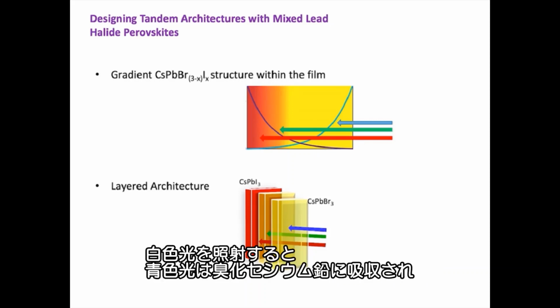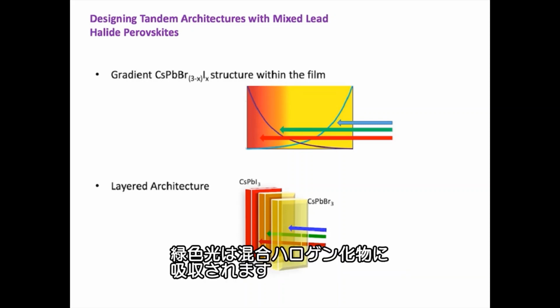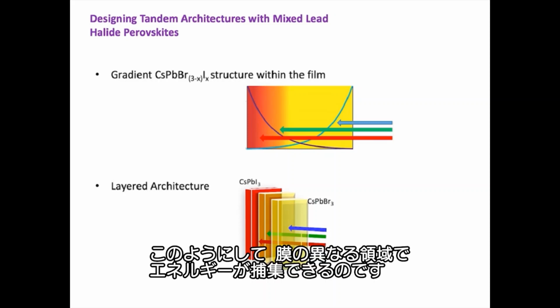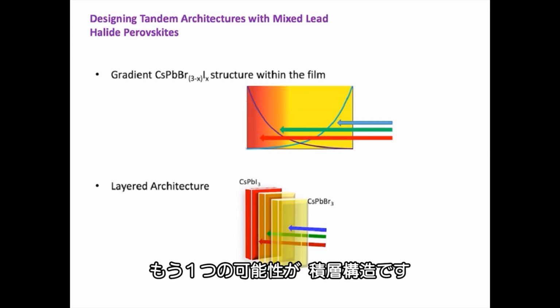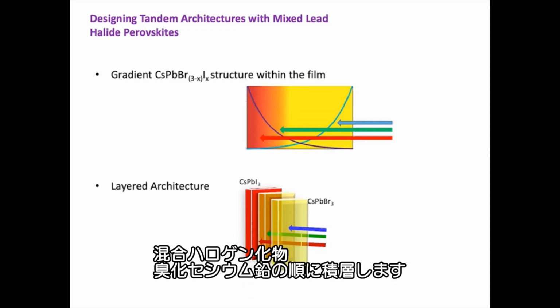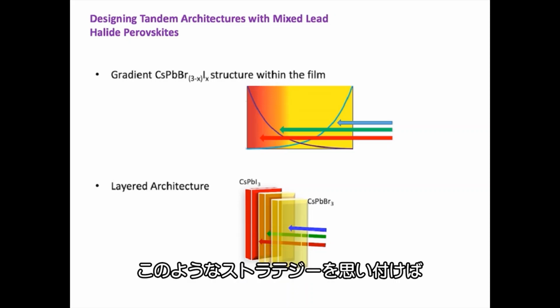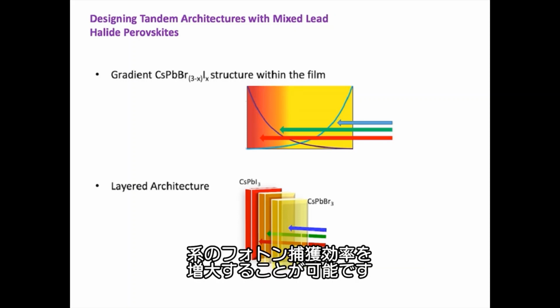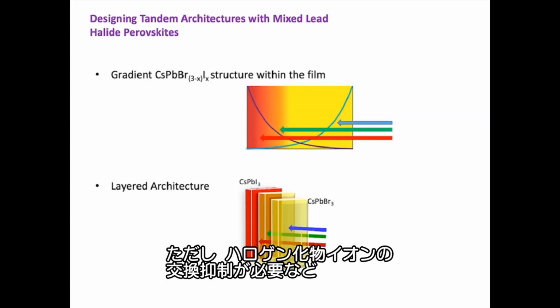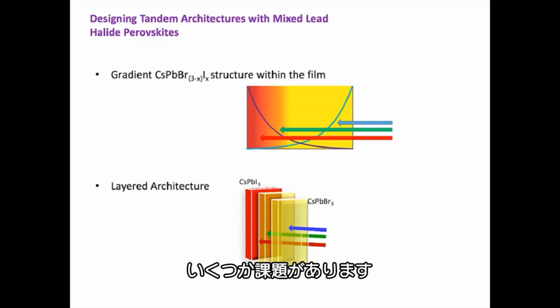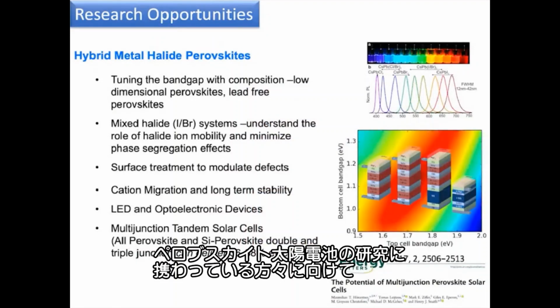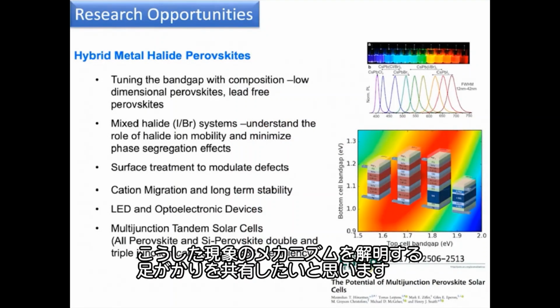So when the white light strikes, the blue light is absorbed by the cesium lead bromide, and the green light is absorbed by the mixed halides, and the red light is absorbed by the cesium lead iodide. So this way you can harvest energy in the different regions of the film. The other possibility is having a layered architecture. So you first put a layer of iodide, then a mixed halide, and then a cesium lead bromide. So again, one can come up with these strategies to harvest photons with greater efficiency. But there are some problems like halide ion exchange, and that needs to be suppressed in this case. So if you are working in the area of perovskite solar cell research, here are some of the opportunities that still need good understanding of how and why these things happen.